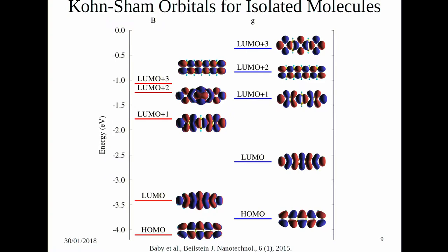Here I have plotted the frontier orbitals of the gas-phase V-shape molecule and the planar molecule. The main result is that the HOMO-LUMO gap has been reduced by half an eV, and there is a LUMO+2 and LUMO+3 exchange, just from the V-shape bending, since both are gas phase.